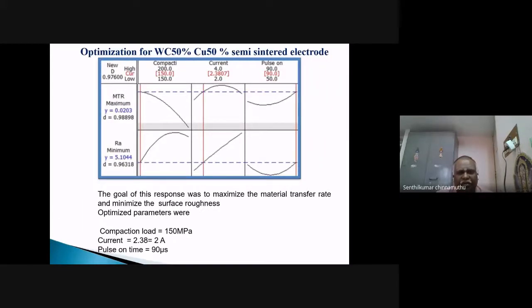See, after optimizing the process parameters, the red color indicates the optimized parameters, that is 150 compaction pressure, current 2.38 amps, and pulse on time of 90 microsecond. The blue color indicates the metal transfer rate, that is 0.0203, and the surface roughness of 5.104.